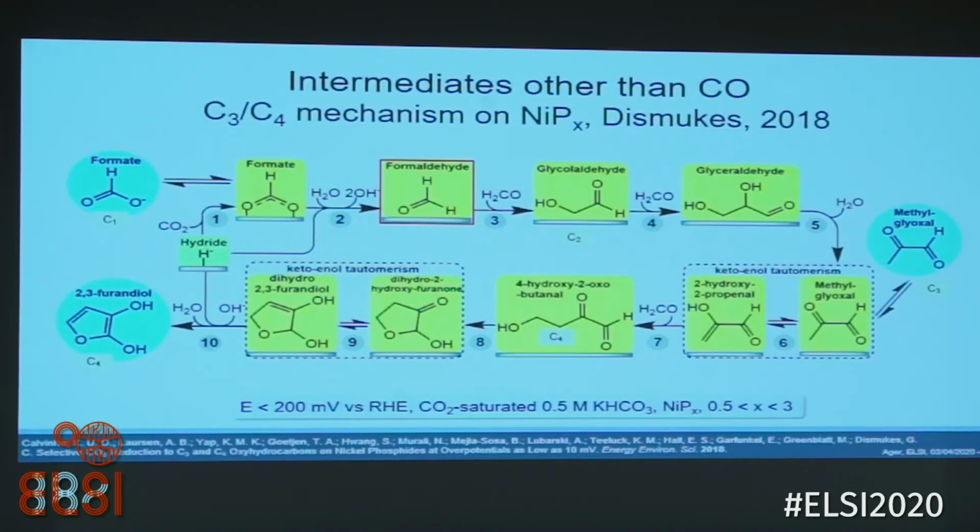Finally, I want to mention, what about getting away from CO? The intermediate in the cascade catalysis that I and others have done is almost invariably carbon monoxide, because we have electrocatalysts that are pretty effective at making it. Noble metals, silver, and gold coming to mind. I'll show you here a proposed mechanism, not saying it's correct, that used a very interesting intermediate to make some very large products relative to what we usually do in CO2 reduction catalysis.